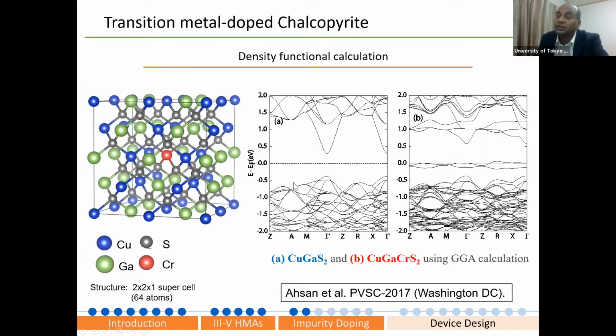And here, the first principle calculation, if we have just CGS, okay? So you see a direct band gap here. But if you put some amount of, let's say, transition metal, in this case chromium, now you see you have an extra band between the valence band and conduction band. Now we have an extra band due to this impurity. And this is how we can make an impurity band solar material. And then you can make two-step photon absorption.